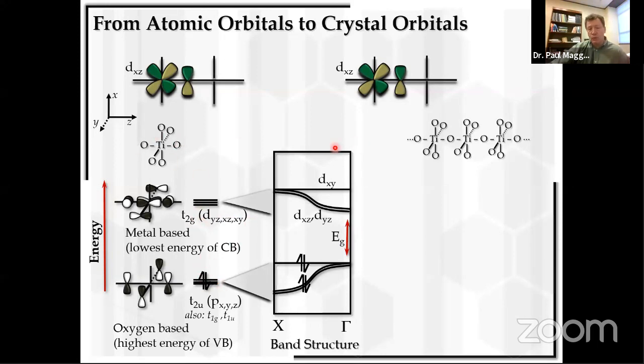Now, when you extend it into 1D, what happens is you have to consider the overlap between the neighboring units. And at the X point in K space, what happens between the neighboring units is that you see that they're out of phase here. So one d orbital is one phase, and then the next d orbital has switched the sign of the phase of the orbital. And so they can overlap in an anti-bonding fashion. And so at the X point of the band structure, the d orbitals are pi anti-bonding.